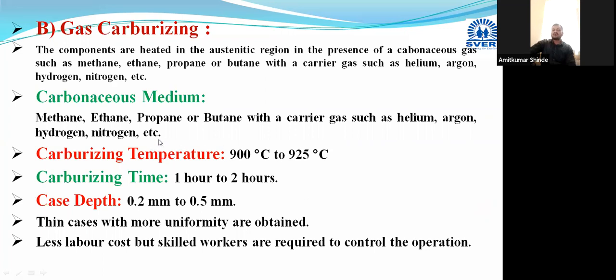Now in this carbonaceous medium, as in solid carburizing, we have discussed that depending on the carburizing temperature and carburizing time, case depth will be achieved. Here also case depth depends on carburizing time and temperature, and along with this, the circulation of gas plays an important role in the case depth. For that, proper circulation of these gases with the help of the carrier gases is required.